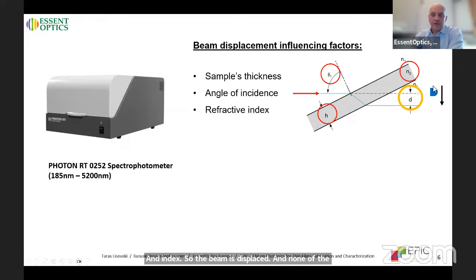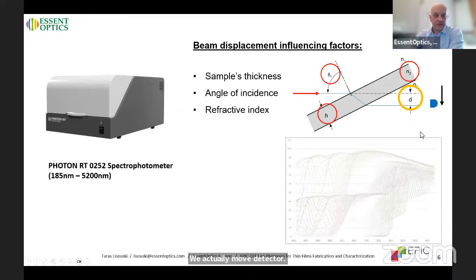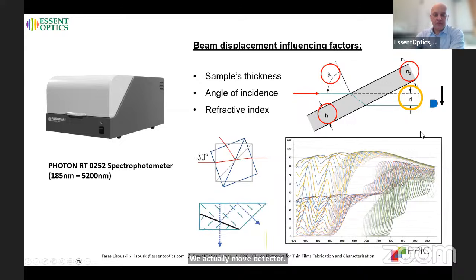What we do, if you look at this blue dot, this is a symbolic image of our detector. We actually move the detector to catch the beam, and our detector is capable of tracking this beam all the way with the change of the angle of incidence. And this feature helps us to measure even polarizing cubes at different angles of incidence or semi-prisms. The image on the right-hand side shows the transmission measurement of SP and average polarization of the cube from 0 to 20 degrees with a 1 degree step.